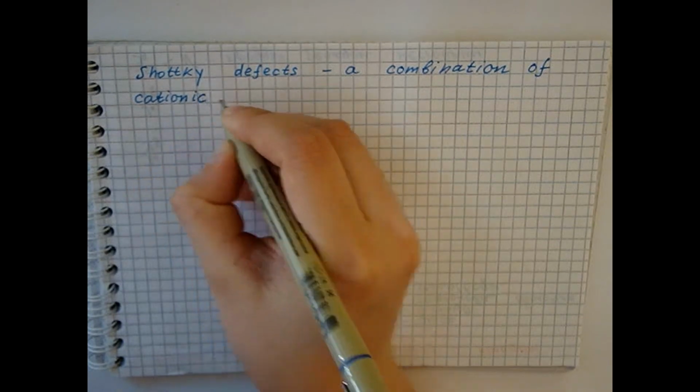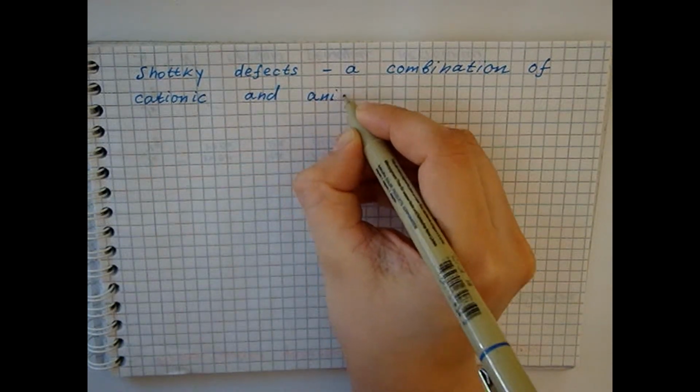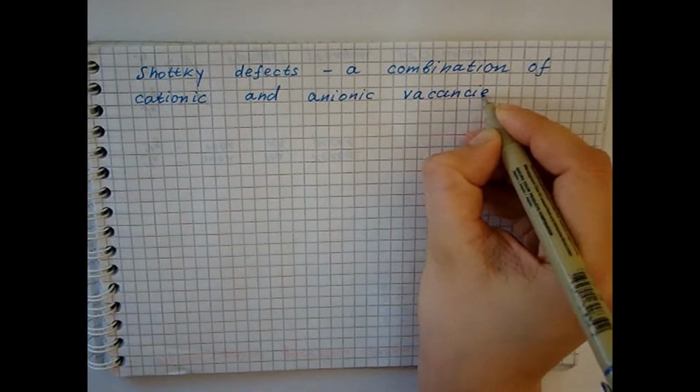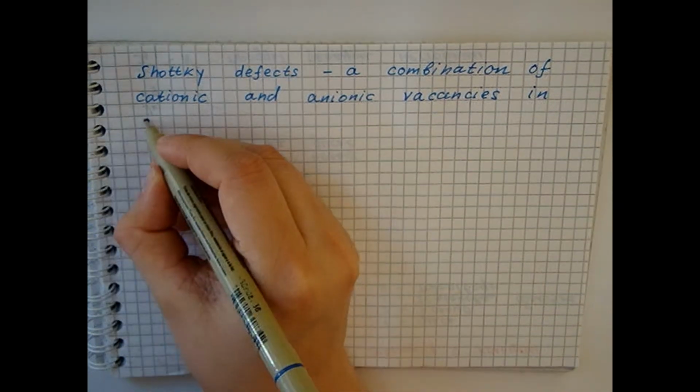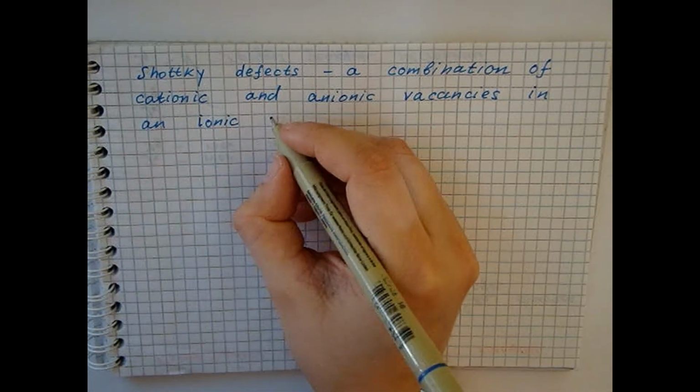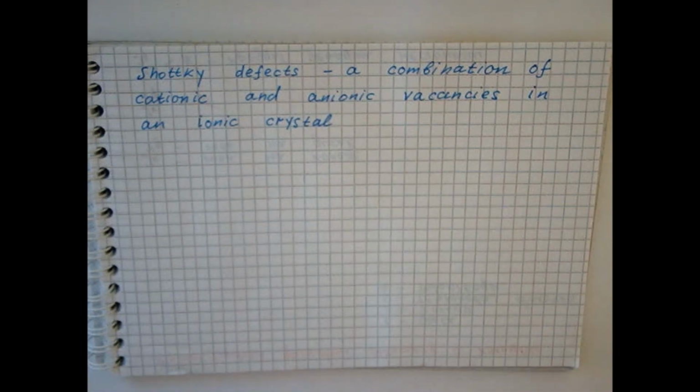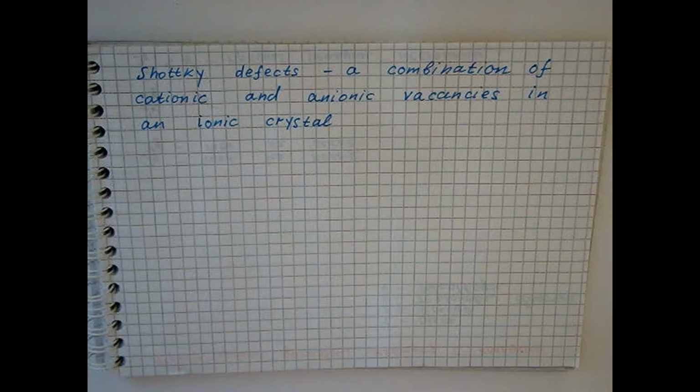Schottky defects are formed as a result of thermal fluctuations. Ions leave the lattice sites on the surface of the crystal, forming vacancies inside it. The process of current flow in such a crystal can be considered as sequential transitions of ions of the crystal lattice to a neighboring vacancy. In general, the mobilities of cationic and anionic vacancies are different, which predominantly determines the cationic or anionic conductivity.